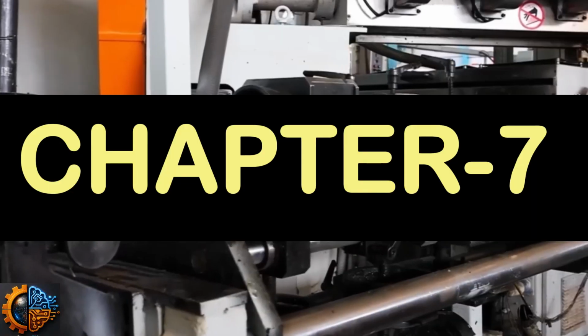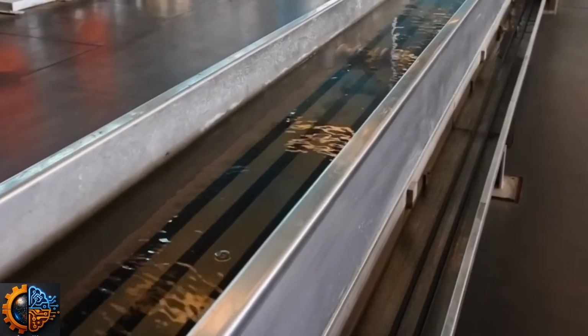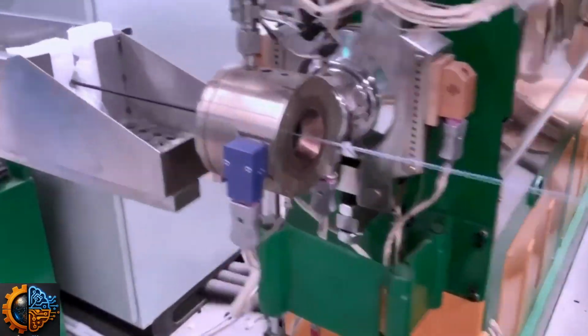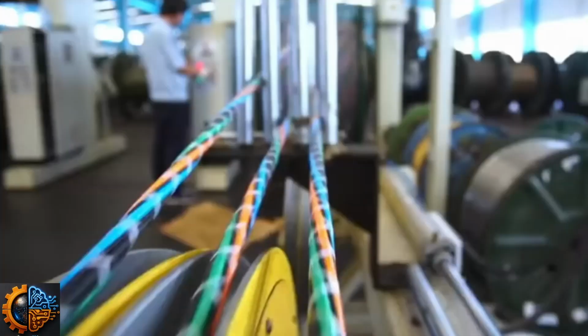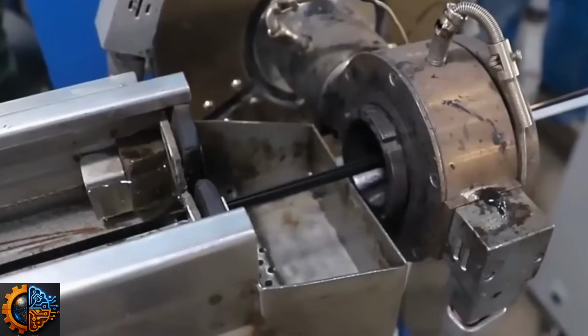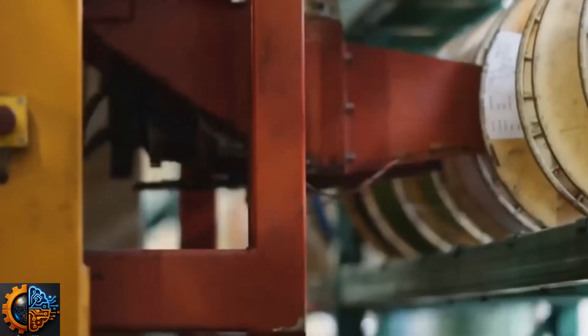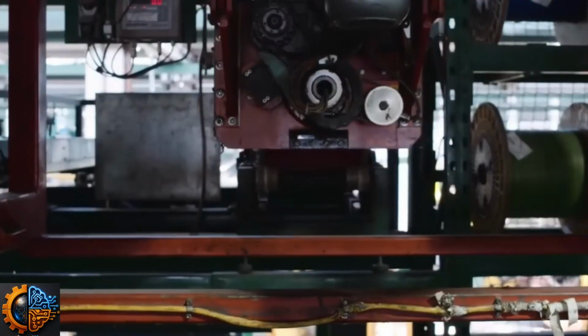Chapter 7: Proof Testing and Color Identification. Each optical fiber must now prove its strength. The production line applies approximately 100,000 pounds per square inch of controlled tension. Any microscopic crack immediately causes failure. Defective sections are automatically removed before the fiber continues.